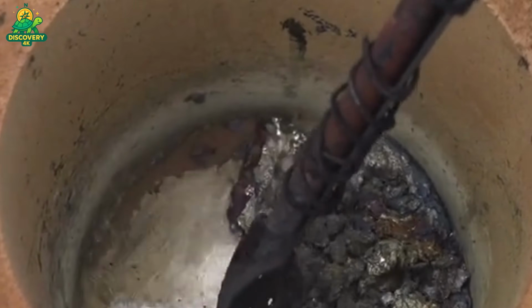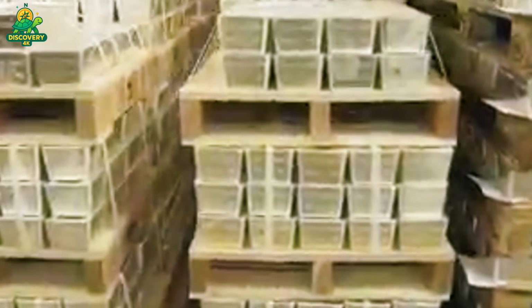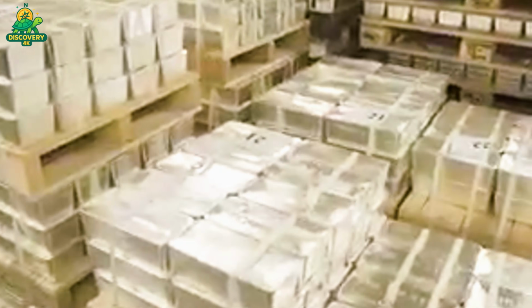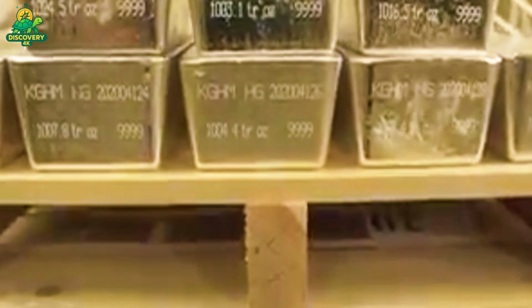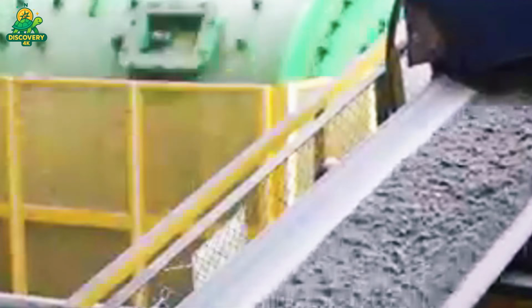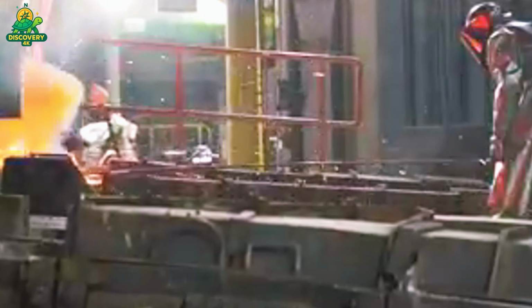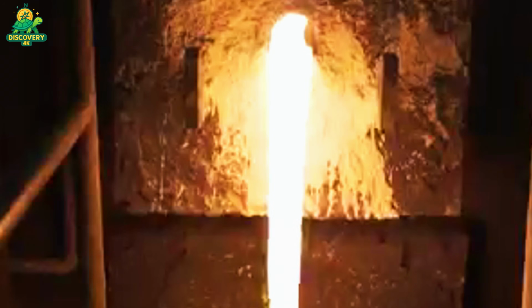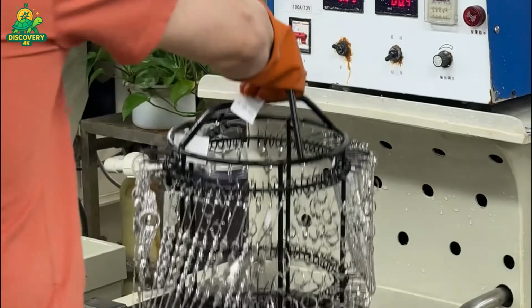Refining begins with electrolysis. The rough silver ingots become anodes, electrodes that dissolve when electric current is applied. They're suspended in a tank of silver nitrate solution, alongside thin sheets of pure silver, which act as cathodes. As electricity flows, silver atoms from the impure anodes dissolve into the solution and redeposit themselves onto the cathodes in pure form. Over the course of several days, these cathodes grow into thick, gleaming sheets of high-purity silver. Meanwhile, any impurities either fall to the bottom of the tank as sludge or remain suspended in the liquid. The refined silver is then melted once more and poured into standard bars, each one stamped with its weight, purity, and a unique serial number.